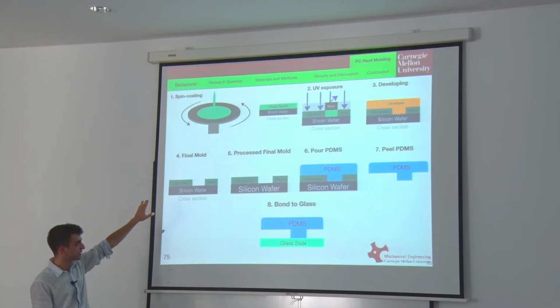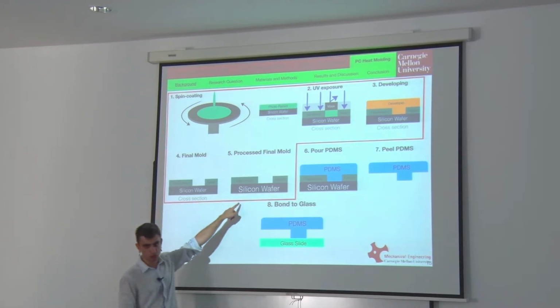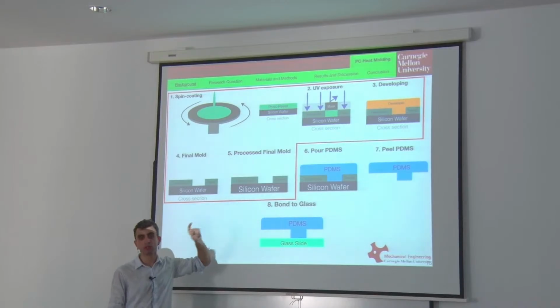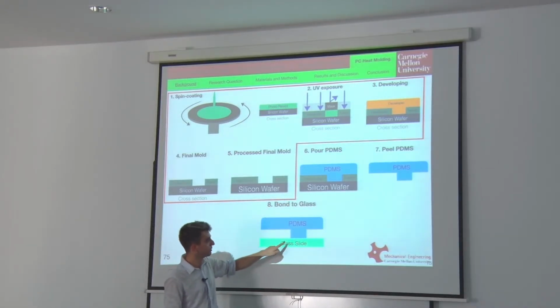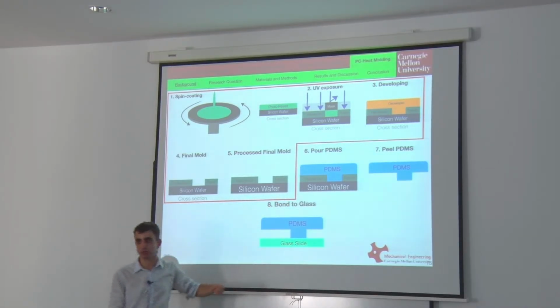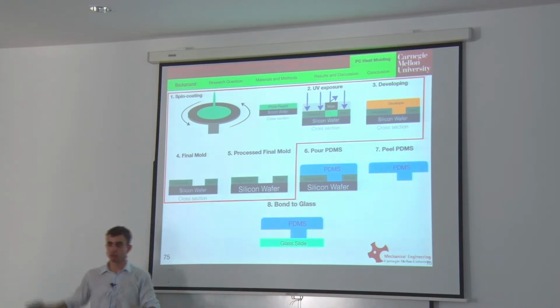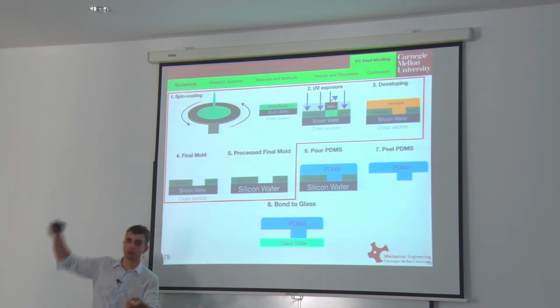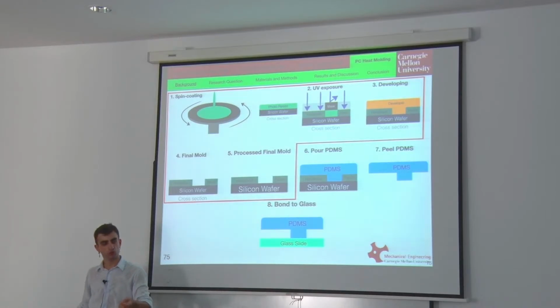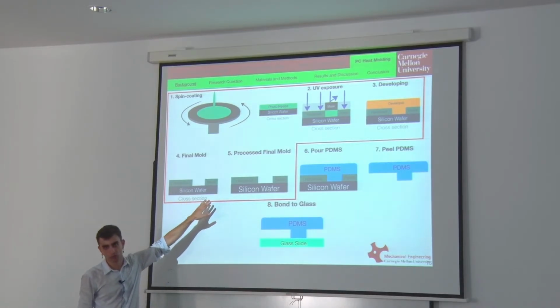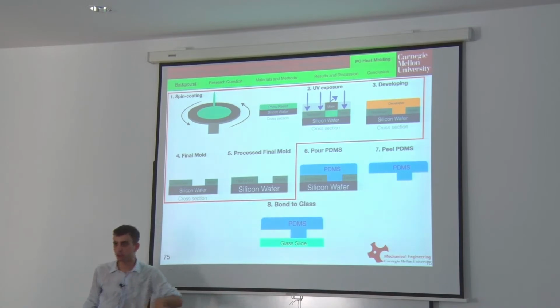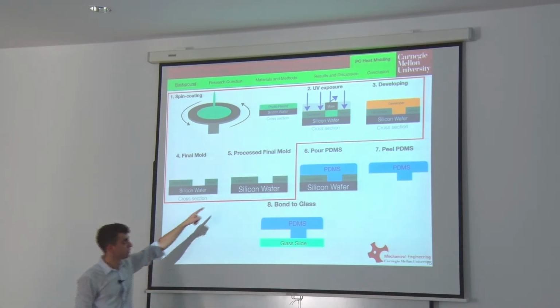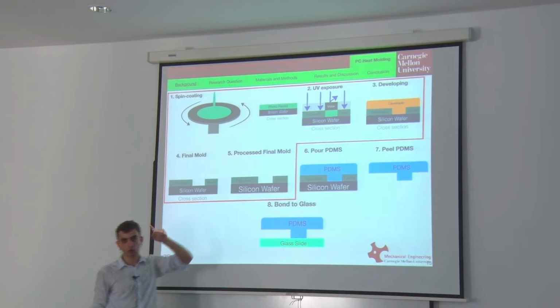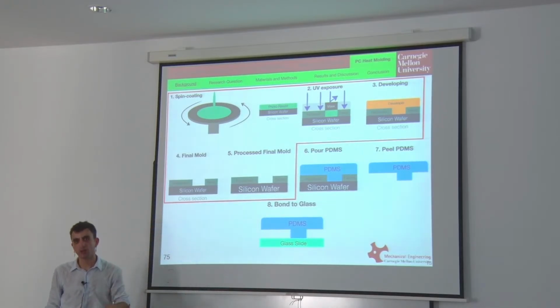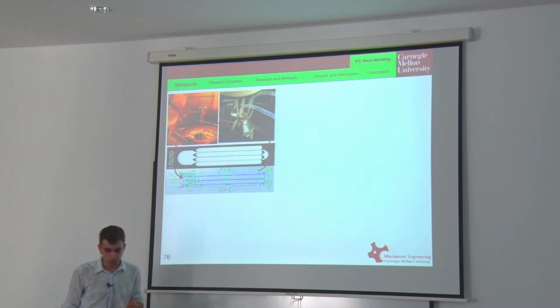And what happens is at the beginning we create this mold. Once we have this mold, it can be used to fabricate these polydimethylsiloxane (PDMS) microfluidic devices as much as you want. You pour PDMS, you cure it, you remove it, you pour another batch of PDMS, you cure it, you remove it. You can use the same mold hundreds of times to make hundreds of microfluidic channels. But in order to make this mold, you have to go to the clean room, and it's a really hard one. It's a pain to get a functional mold.